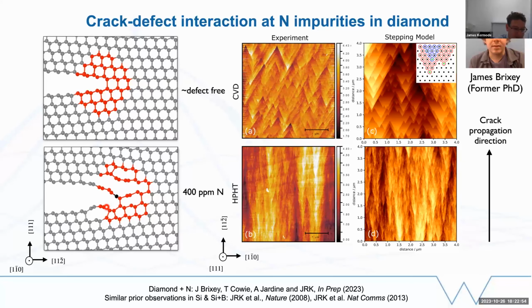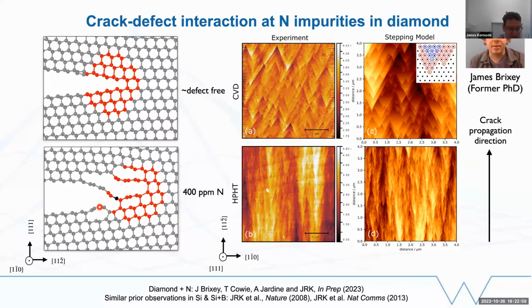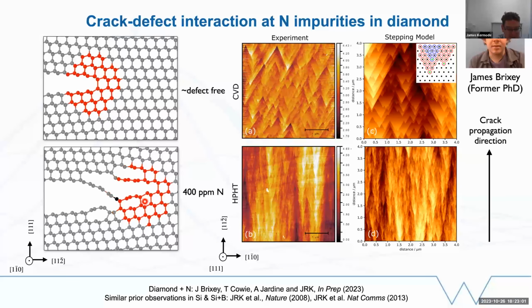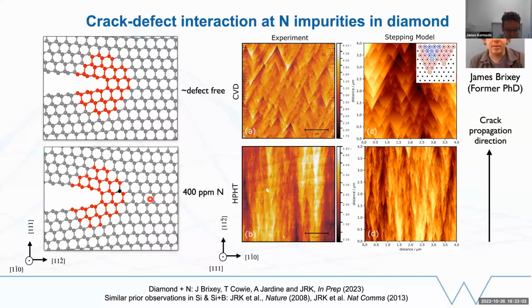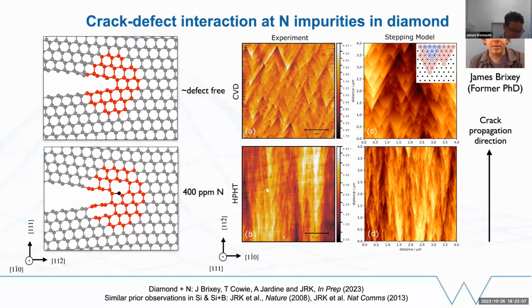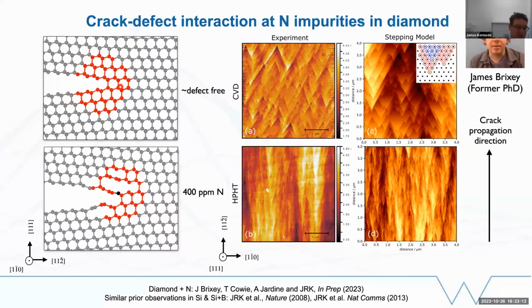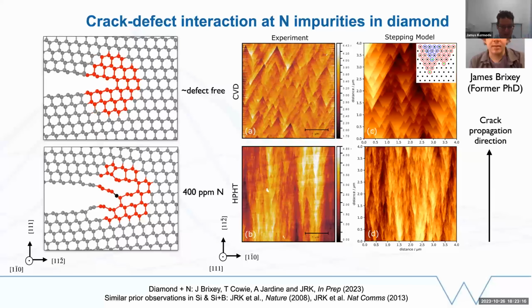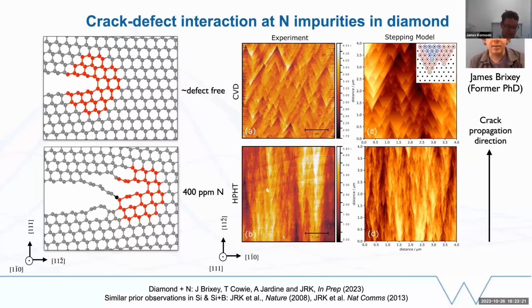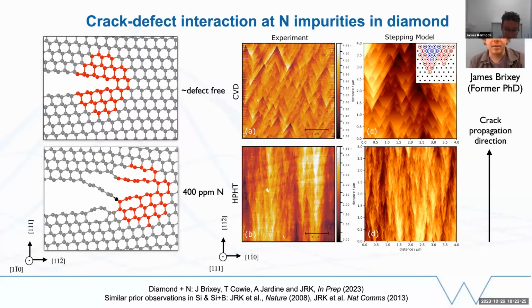It's nice that we can put in impurities, we can put in defects, but we are limited in the duration of the simulations. So these are quite expensive DFT simulations. They can only run for a few picoseconds. What I want to move on now is something that lifts another limitation of this approach. So here you can see we're looking at quite narrow periodic systems in the plane in or out of the screen that you're looking at. It's a quasi two-dimensional setup. It's periodic along that line. How can we lift that limitation while still keeping things affordable?